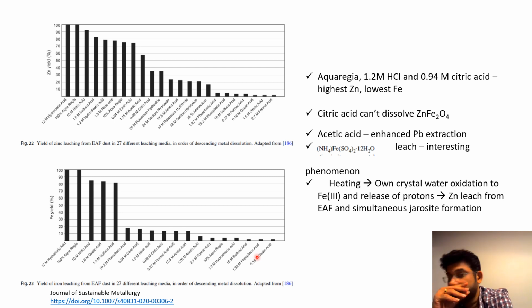So what they found is that aqua regia, the particular concentration of hydrochloric acid and citric acid, had the highest zinc and the lowest iron. The key thing is that citric acid is a bit, let's say, benign, but it can't dissolve the zinc in ZnFe2O4, again the same issue. And then they found that if you have lead in the stream, acetic acid can do enhanced extraction as well. There is a specific reason for it, but it's too detailed to go into.